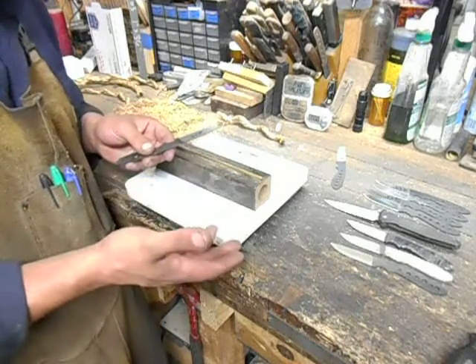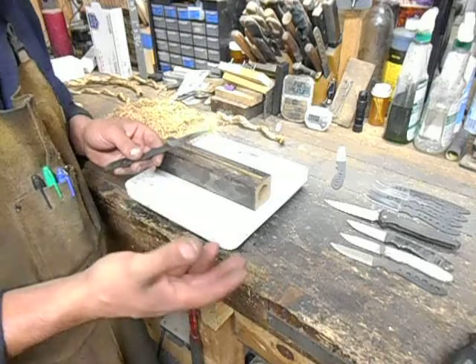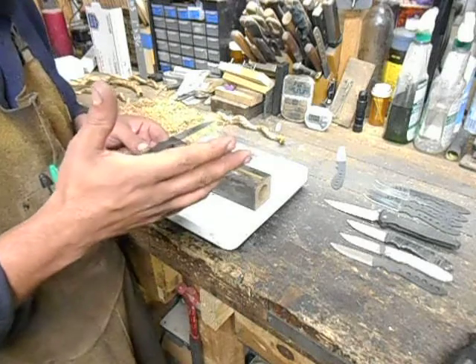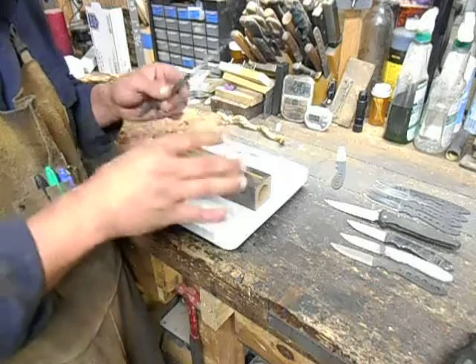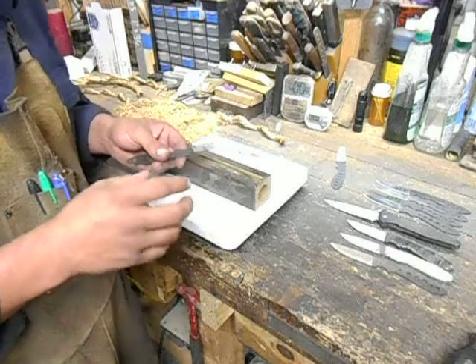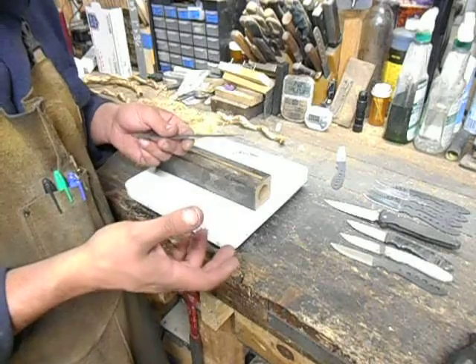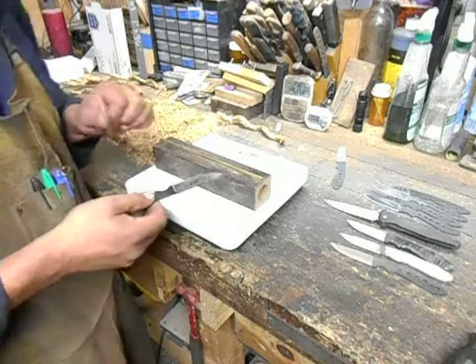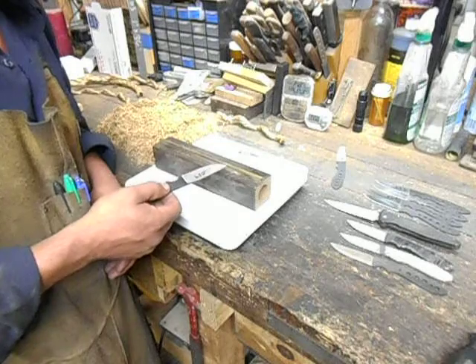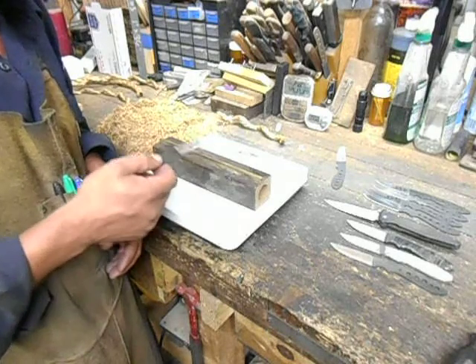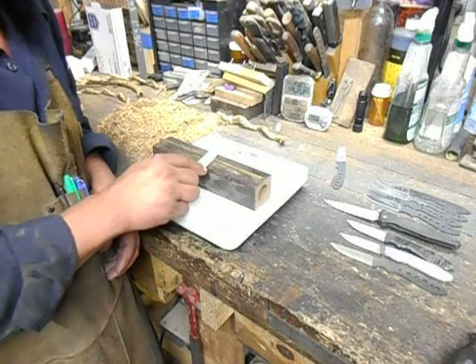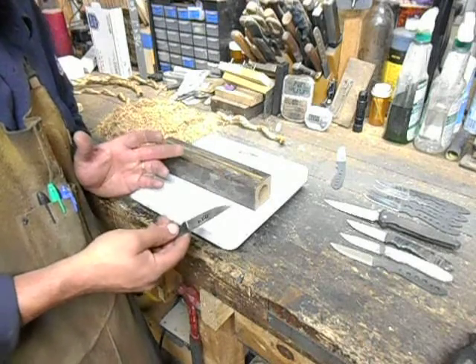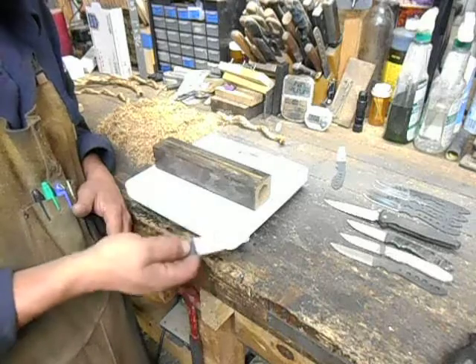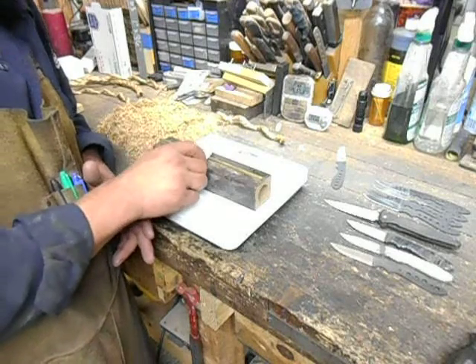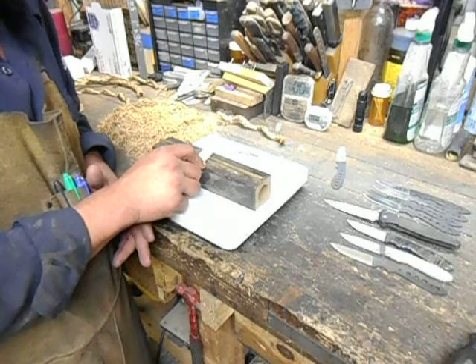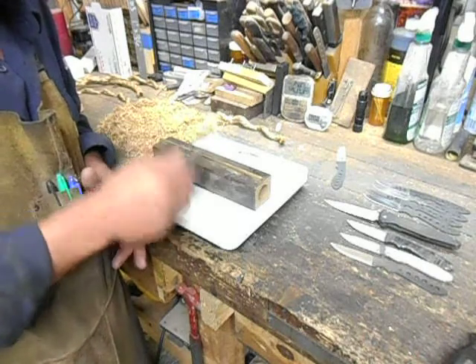If the edge chips, it's too hard. If it stays bent over, it's too soft. If it flexes up and then returns to true, then you're in a pretty close range of where you want that edge to be for your edge stability. Now, if you take that farther, testing for the edge flex just at a predetermined angle tells you that you're kind of close. If you want to take that test farther and learn more about your steel, then you keep increasing the angle and increasing the pressure until that edge deforms.